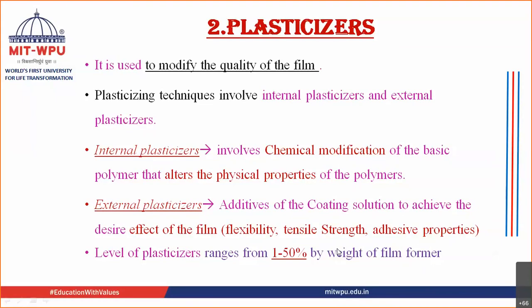Plasticizers also increase the adhesive property, whereby the film can stick onto the tablet. So we use external plasticizers, adding them to the coating solution to achieve flexibility, tensile strength, and adhesive property. The quantity of plasticizer added ranges from 1 to 50% by weight of film formers.